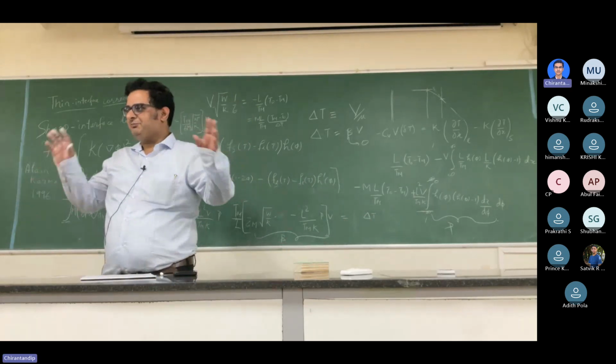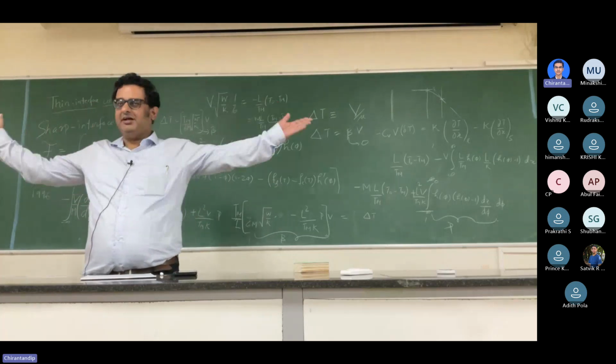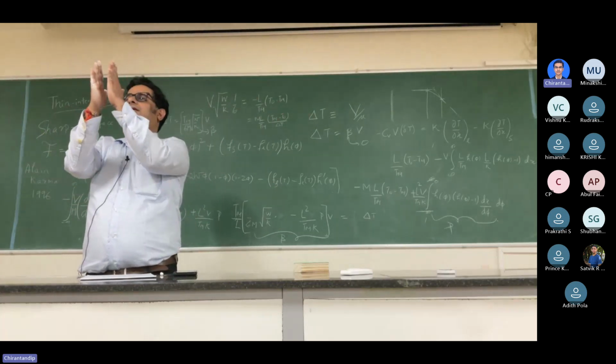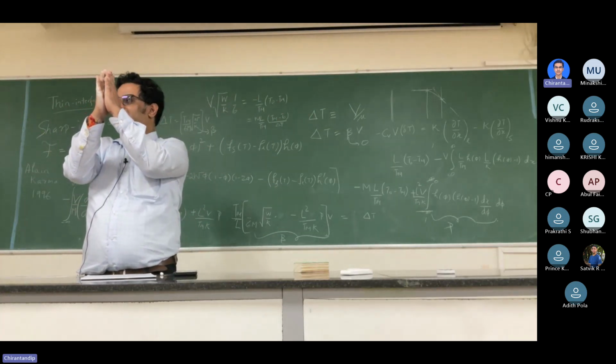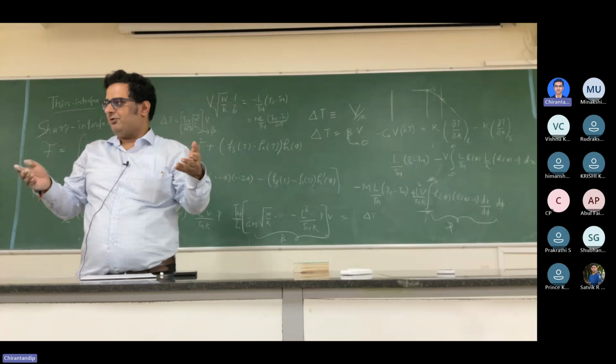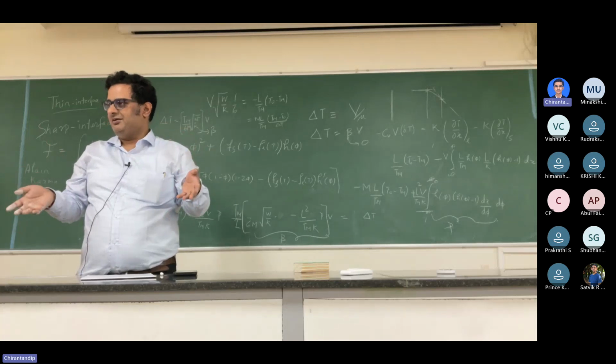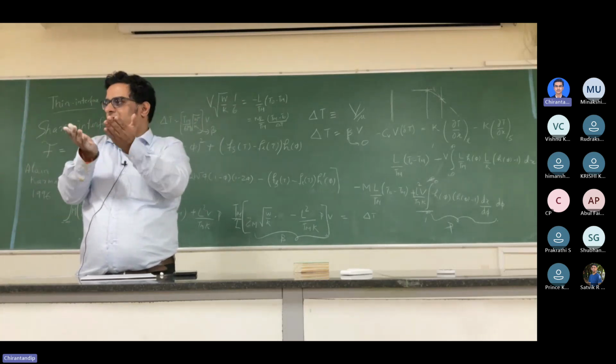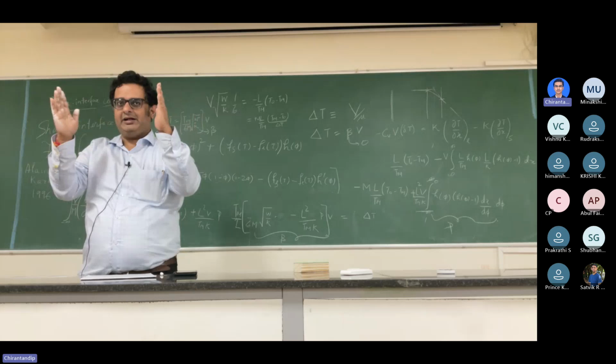All right. The idea is pretty simple. What you did was, instead of making an interface rather small, over here where the temperature is rather constant, you allow for the interface to be a little bit wide, which is realistically what you will be using anyway for your simulations. Because if you use zero interface width, you can't do simulations. It will be finitely wide anyway.